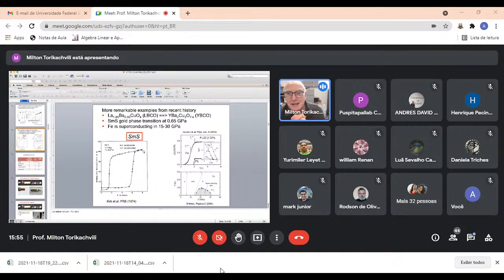Okay, you may ask, well, how do you know? Why do you call this the gold phase? Well, there's one type of pressure cell where you have a diamond window. So you can see through that as soon as the pressure reaches 6 kilobar, the sample becomes gold colored.